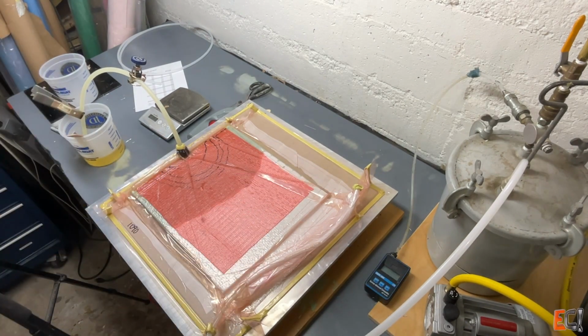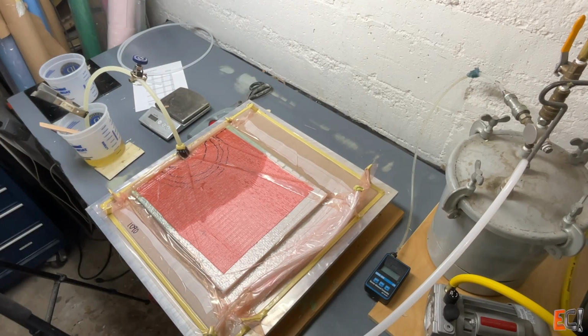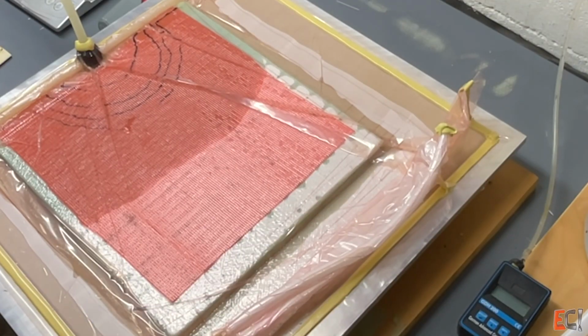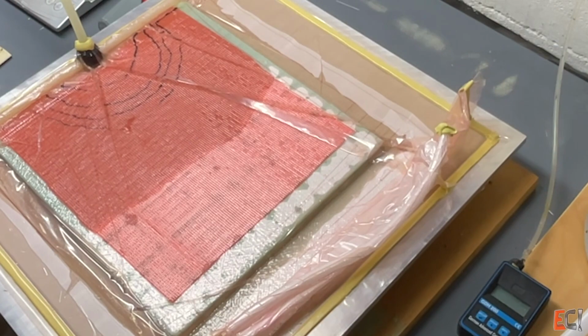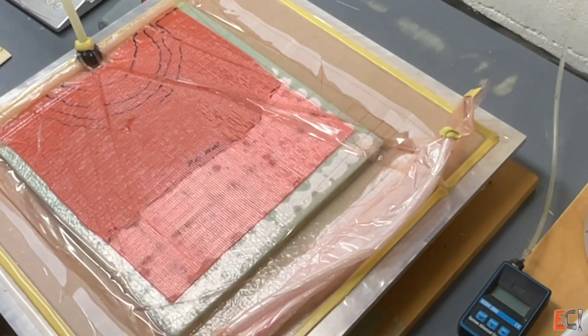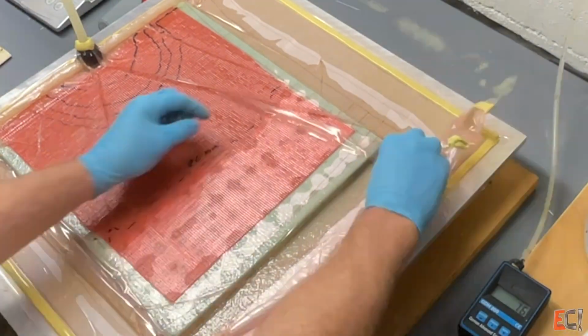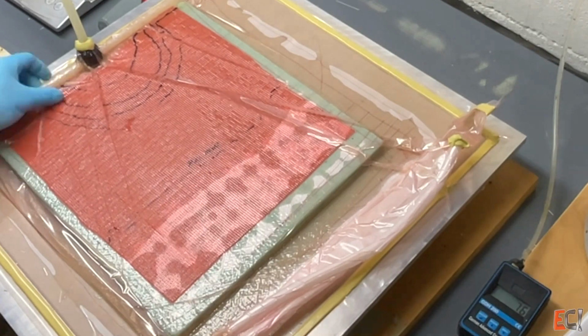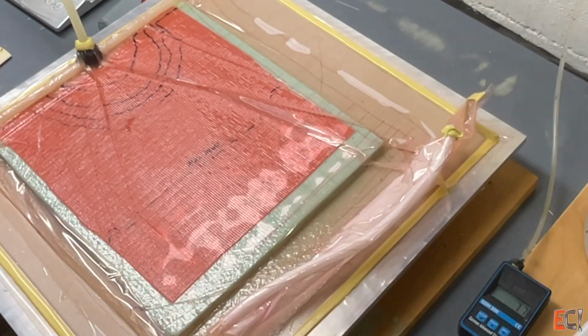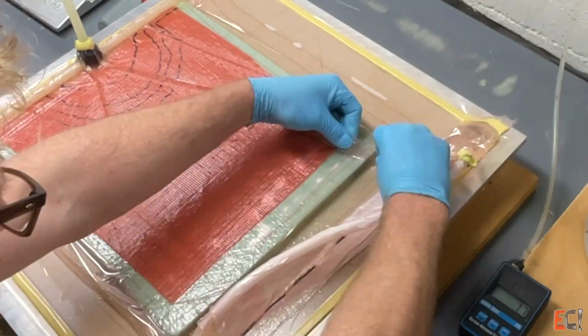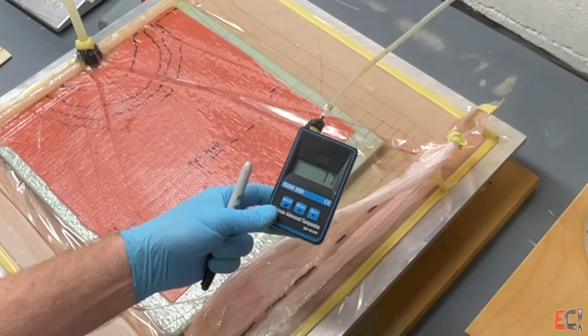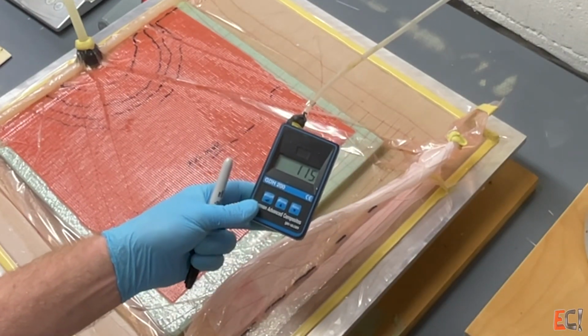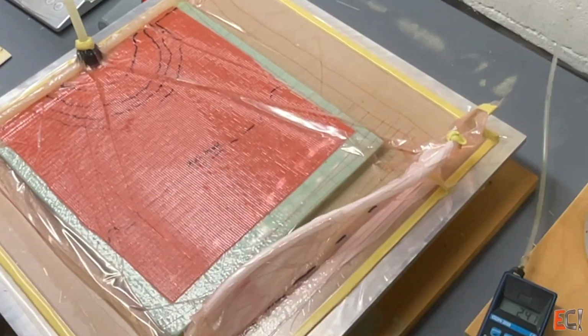So I'm having to lift that little black connector up and bridge the bag a bit and let resin flow out around, and that's not awesome. As this fills more than halfway, you can see a little grid of resin popping up from the bottom. What's happened here is the resin has flowed underneath through those big gaps in the core, and it has come around the bottom and blocked the air from escaping.